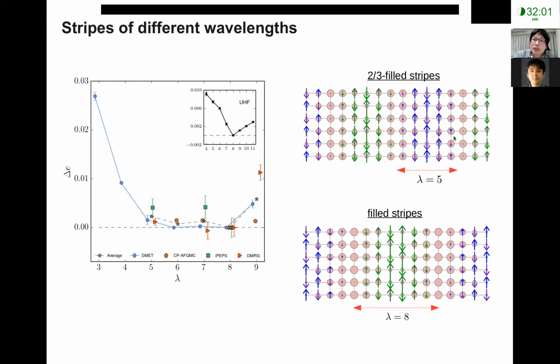So these two systems are exactly the same system with the same coupling and the same density, but we can stabilize these two very different states in DMRG, and we find that their energy is extremely close. This is also observed in almost all the methods we consider, that stripes of different wavelengths are almost degenerate in this region, with wavelength from 5 to 8.